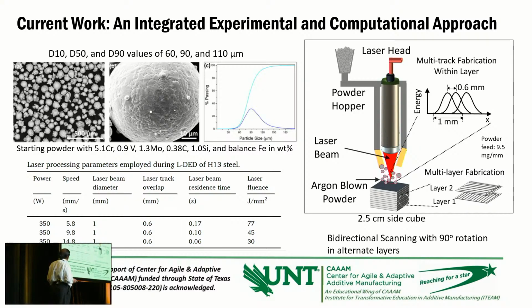And speed controls the kinetics of the process, how fast the beam is varying. So you are varying the energy input as well as the kinetics of the process, and each one will produce a different kind of microstructure. In this direct energy deposition process, we did not use the powder bed, but the powder is injected coaxial to the laser beam, and both move together in a linear fashion back and forth and create one layer, and then you deposit another layer and so on.